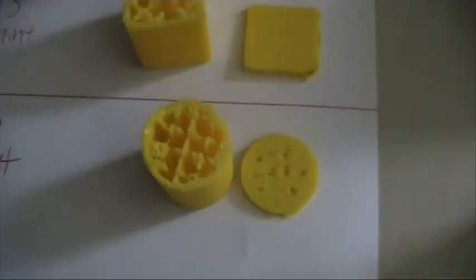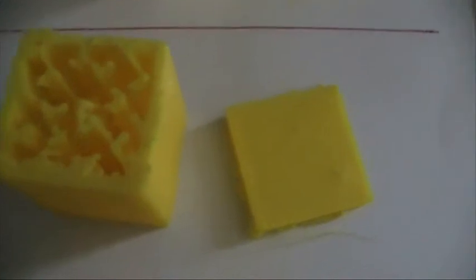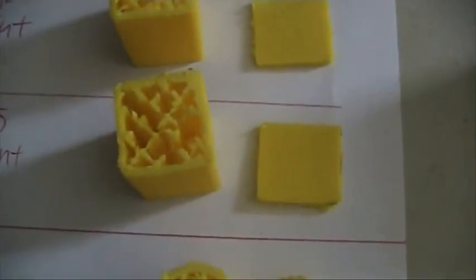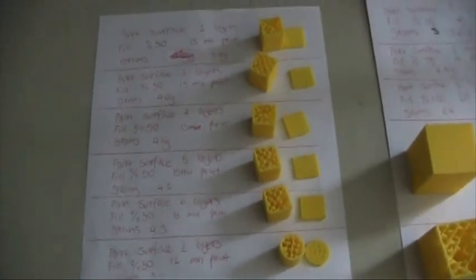So for a round bit, you probably want to go for 4 layers instead of 2 layers, as with 4 layers over here, some bits are a bit thin, you can see through, but it covers consistently. At 6 layers, it is completely solid, but slightly warps. If I did a slower print, because I printed everything fast, it would not warp whatsoever.